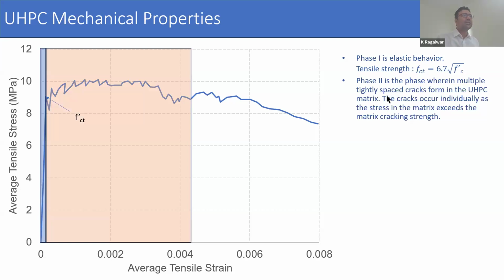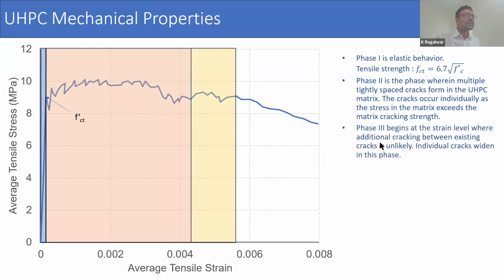Phase two is where multiple tightly spaced cracks form in the UHPC matrix. The cracks occur individually as the stress in the matrix exceeds the matrix cracking strength. So once the matrix cracks, matrix meaning the concrete itself, the discontinuous fibers start bridging the crack, and if there is enough bridging capacity in the matrix, what it does is that it allows the concrete to crack at some other location. Then again at that other crack location you would see fiber bridging, and again at that crack location, if the fiber bridging capacity is high enough to initiate a crack at a third location, then we see multiple cracking until we reach phase 3, where you see that there are no additional cracking, but individual cracks